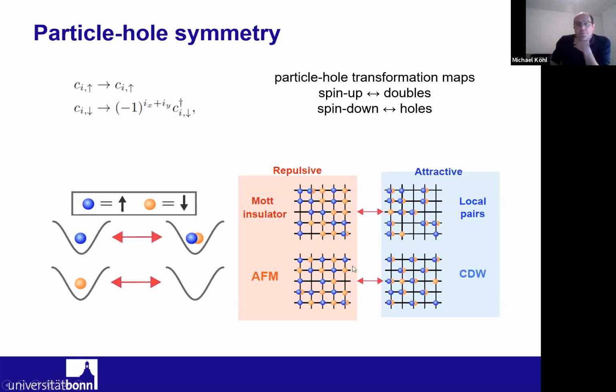We can take this even further if we ask what happens to our antiferromagnet, where the spins are really alternatingly ordered across the lattice. Then we actually end up with an arrangement of pairs on every second lattice site. And this is a charge density wave state of the pairs. So we get here a mapping between very different phases. For example, the charge density wave phase would be a compressible phase in the charge domain, but the antiferromagnet, of course, is an incompressible phase in the charge domain. But we will see that we can actually map these properties onto each other very well.